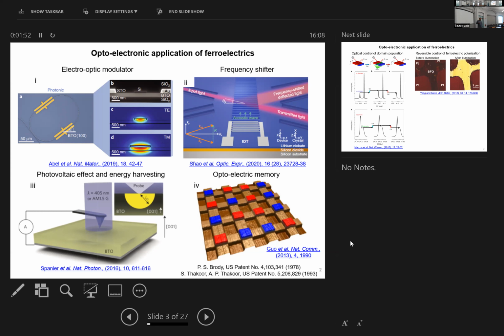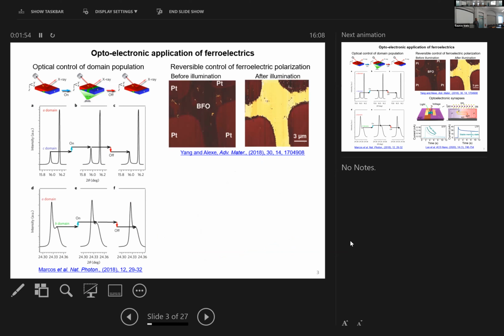What people have been doing is they are trying to understand how it works. For example, in this particular case, they did a synchrotron measurement on a barium titanate crystal, where they showed that with light, the intensity of A and C domains, A and B domains varies. So you can see by turning the light on, it goes up, and off, it goes down. So you can control the domain population with this, and they suggested that it is coming from a ratchet effect across the domain walls.